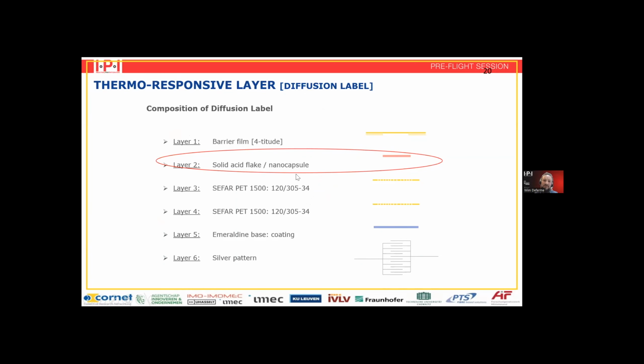And then if the temperature, and that's something that colleagues of mine are working on, if you have a specific nanocapsule, this nanocapsule can contain the acid. And once a specific temperature threshold is overcome, this nanocapsule will open, and then the acid is released through the SEFAR pads onto the emeraldine base, and then transfer it from non-conductive to conductive, such that this interconnection is closed. We didn't go that far, so we are still in the research phase for these nanocapsules, but this